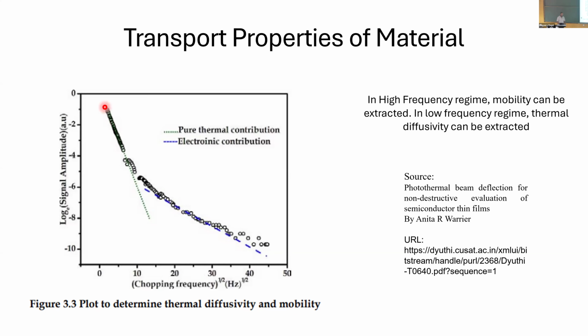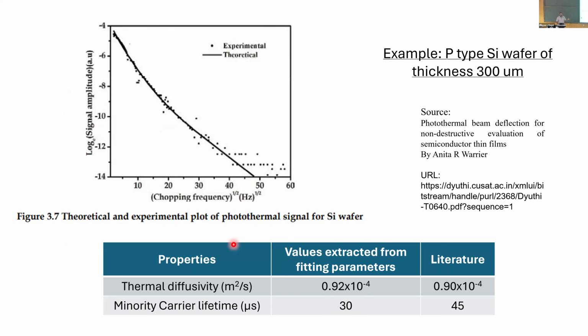So this is heat diffusion dominated versus electronic contribution. If you measure this, you can extract parameters like minority carrier diffusion and thermal diffusivity, and these are measured for silicon and are pretty much in sync with the known measured values. This is what you can do, so it's a versatile technique in a way.